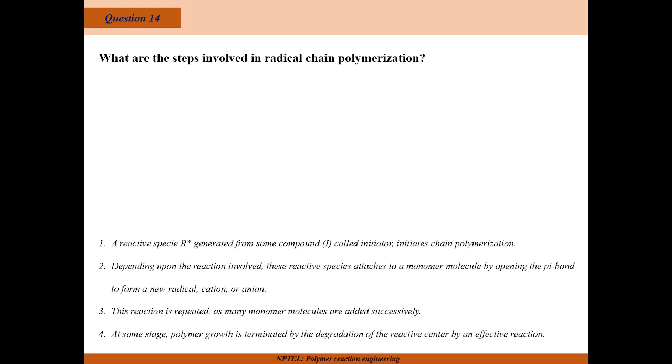Generally, not all the free radicals I create initially will be available straight away to initiate. Sometimes they may recombine and be lost. So the efficiency of the initiator is important, but when it happens, it will initiate multiple monomers at a given time. Some monomers will add more monomers, some will go fast, some will go slow.